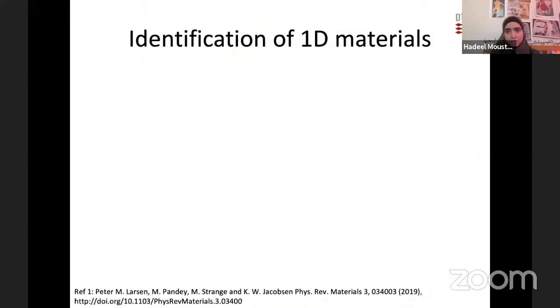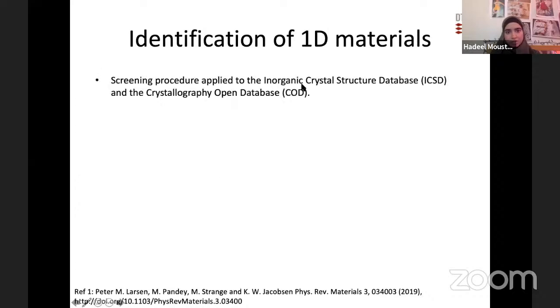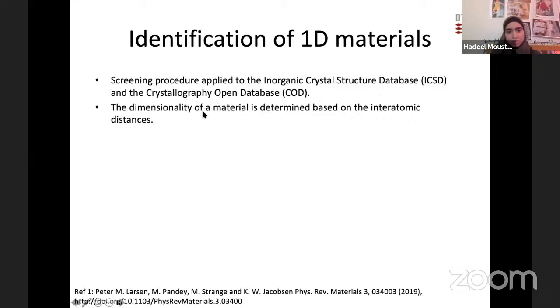So for the identification of one-dimensional materials, all the work has been done by Peter Larsen, where he made a screening that applied for the inorganic crystal structure database and the crystallographic database, where the dimensionality of a material is determined based on the interatomic distances. And he defined a scoring parameter in order to identify all the low dimensionality materials.